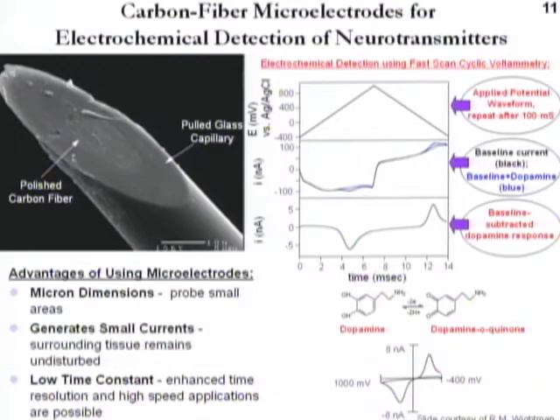What we see here is actually detection of dopamine. Here's one of those carbon fiber microelectrodes I mentioned. There's the carbon disc at the end of the capillary. And here's the linear sweep. We've crossed the appropriate voltage to get dopamine to oxidize, and this is a reversible process. The black scan is the background current. I add dopamine to my system and get a little blip in the appropriate potential region, which is associated with dopamine being oxidized and the reverse reaction, the quinone being reduced back to dopamine. We can subtract out the background, see the current, and it is proportional to the amount of dopamine that's present.